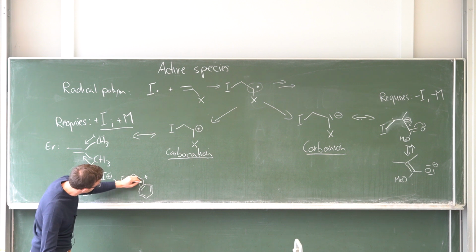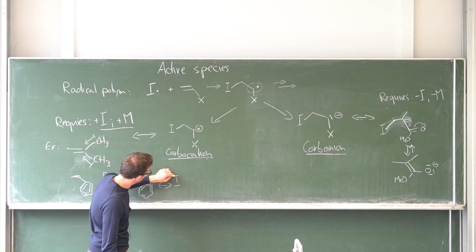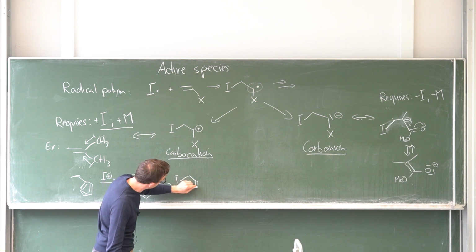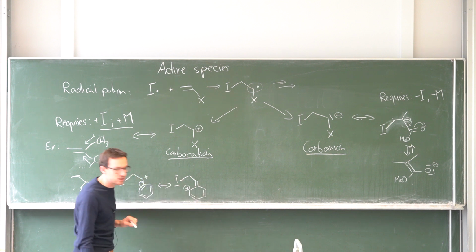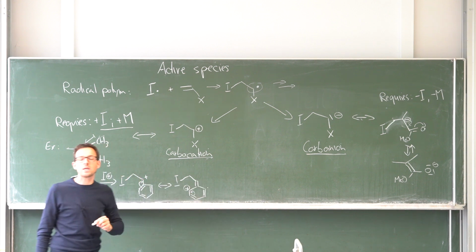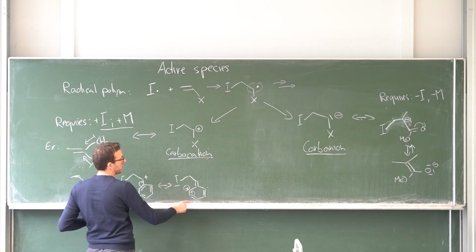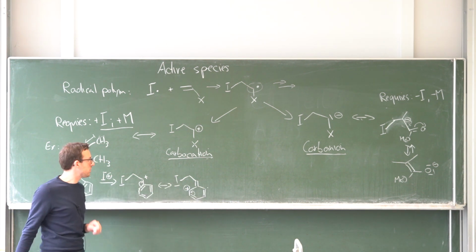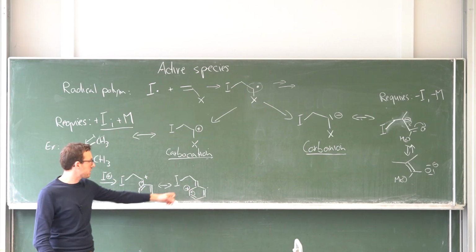the electrons in the ring can move out and delocalize the positive charge, which now sits in the ring. And then likewise this positive charge can jump around in the ring, so it could also be here or it could also be here, similar to what we discussed last week, or 2 weeks ago. So this would be one possibility for a styrene molecule to mitigate a positive charge here.